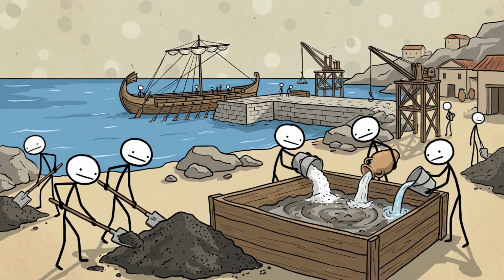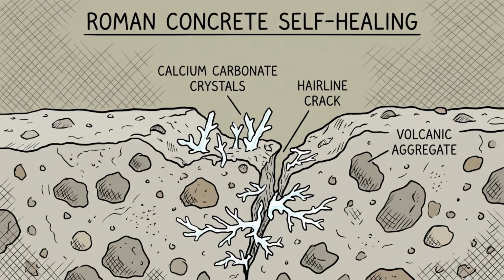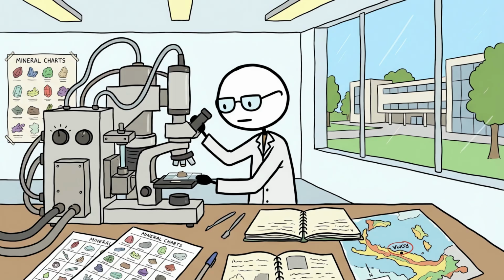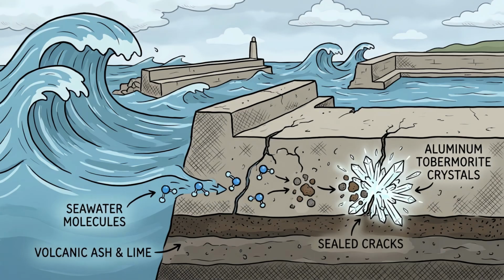The formula combined volcanic ash called pozzolana from specific sources, lime, and seawater. This created crystalline structures that literally grow into cracks, healing damage automatically. A 2017 analysis by Jackson's team in American Mineralogist revealed that seawater triggers growth of aluminum tobermorite crystals in microcracks, sealing them before they can propagate.